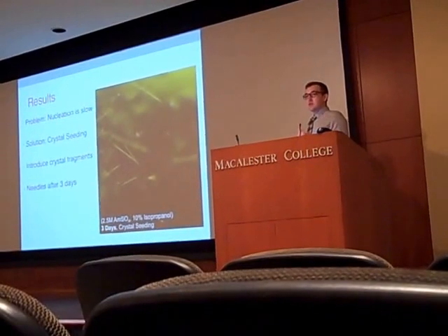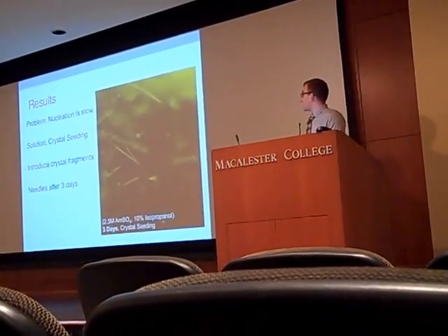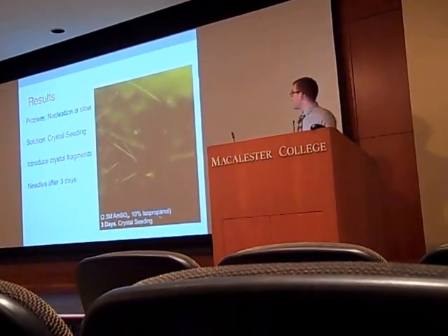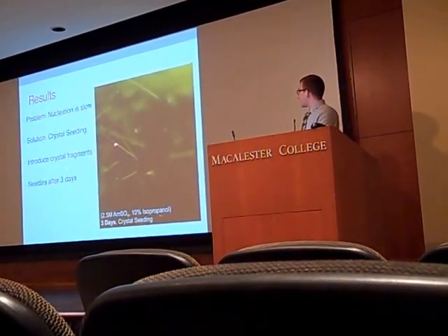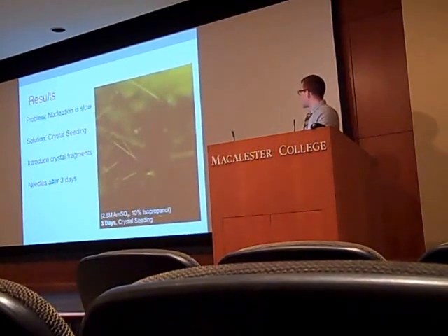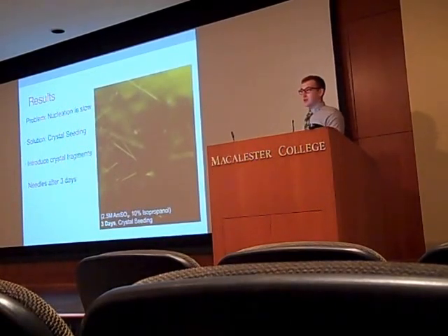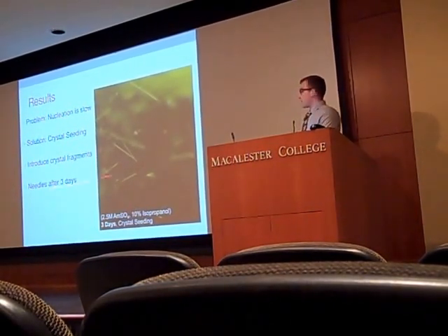You then introduce some of these fragments into an already equilibrated protein drop, where they can serve as preformed nucleation sites from which crystal growth can occur. So I did this, and only 3 days later, what I saw was the growth of quite a few of these needles. There was a whole ton of them. It's hard to get a good picture of a one-dimensional object in a three-dimensional space. But only after 3 days.